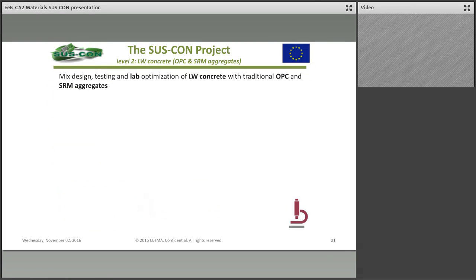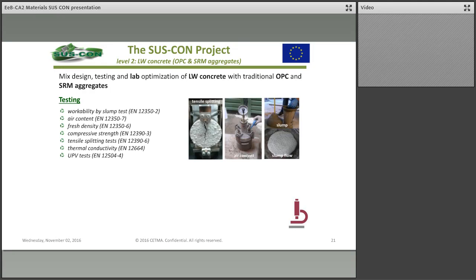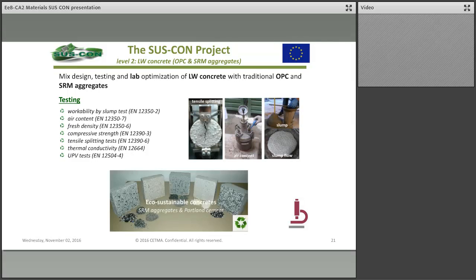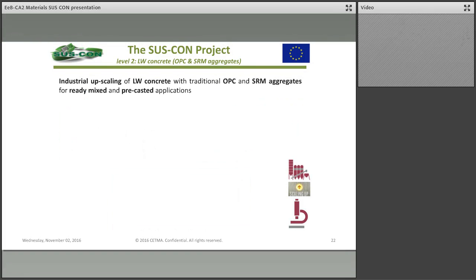And then afterward, several lightweight concretes with aggregates from secondary raw material and ordinary Portland cement were designed and tested in terms of workability, air content, fresh density, compressive strength, tensile splitting strength, thermal conductivity, and the UPV test. And at the end, we were able to develop at the lab scale some eco-sustainable concrete made of secondary raw materials and ordinary Portland cement.